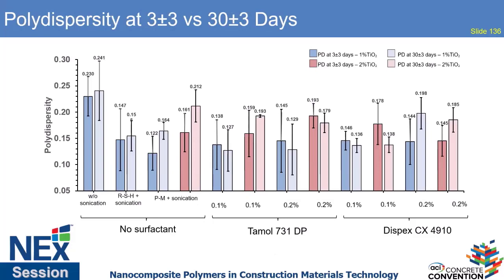The polydispersity at 3 and at 30 days was also measured, and there was not a significant difference between the two. One thing I want to mention is that polydispersity refers to the non-uniformity. Because we didn't have a monodispersed system, we had a polydispersed narrow system, which is typically between polydispersity 0.1 and 0.4. Below 0.1, it's a monodispersed, narrow monodispersity.